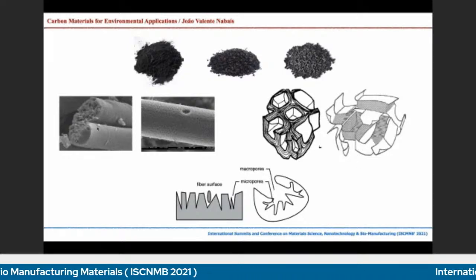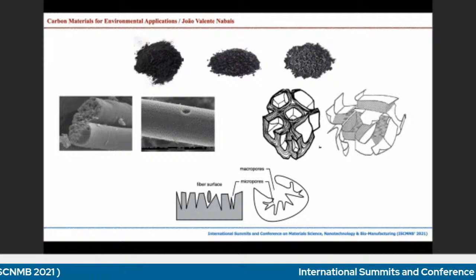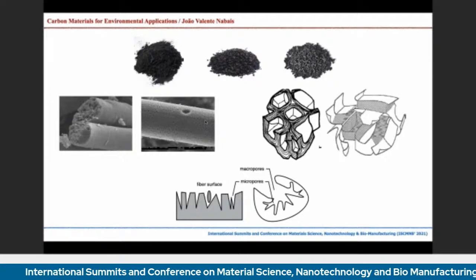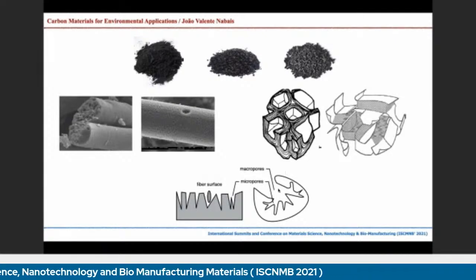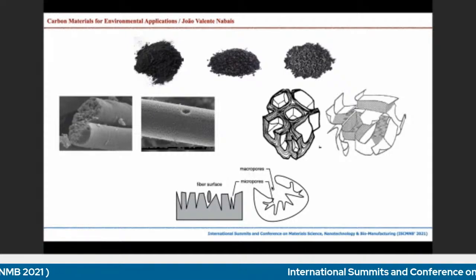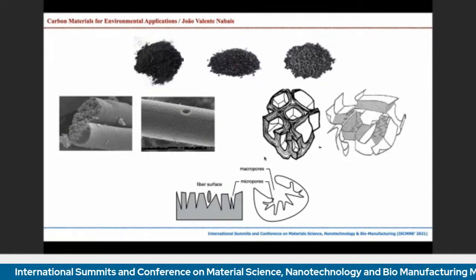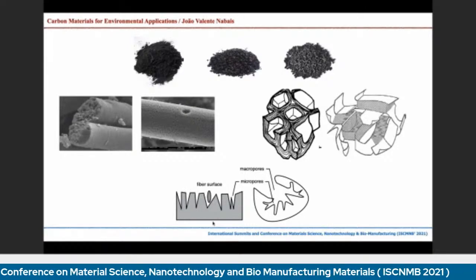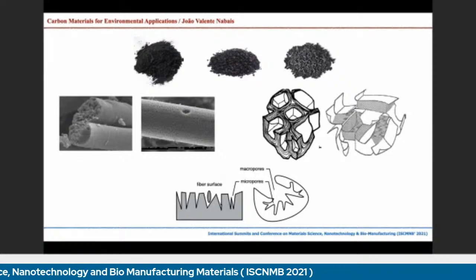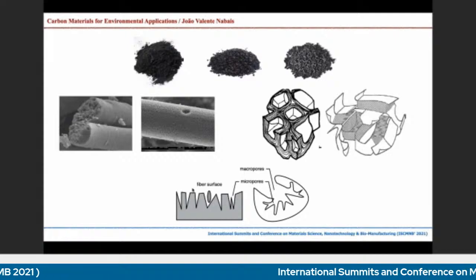Then the difference between activated carbon fibers and activated carbons is the filamentous structure of the fibers. And more importantly, you can see at the bottom that in the activated carbons, the porous network is more complex. It starts with macropores, so big pores, and then goes to mesopores, and finally to micropores, where most of the adsorption takes place. When it comes to activated carbon fibers, on the left-hand side here, the micropores open up to the surface. So in a way, the sites where most of the adsorption takes place open straight away to the surface of the material. And that's the major difference.